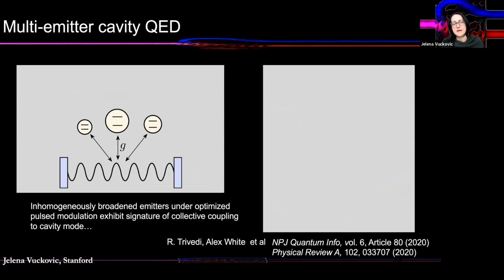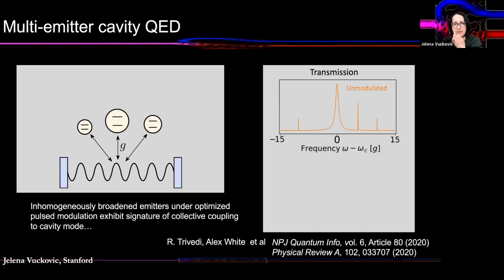And another idea is multi-emitter cavity QED. I said that the state of the art for two color centers coupled to cavity is coupling of two of them to a single diamond cavity, work that was done by Mikhail Lukin and Marko Loncar at Harvard, where they tuned them with the external magnetic field, but that's of course not scalable because it depends on where emitters are and where their frequencies are. We looked at whether we could scale this up for now to 3 emitters, but of course you could do it for more than that, even 10, like in the previous work on transduction that I showed, just by applying a single global drive.